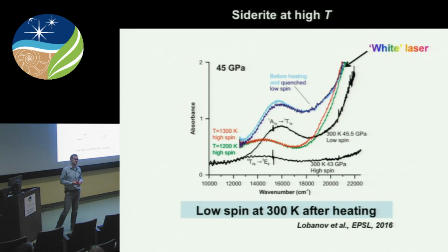Well, we collect thermal background separately, but at this low temperature, at 1200 and 1300 Kelvin, we essentially get zero thermal background because we're using a gated detector. And our white laser is so much brighter than conventional light sources, so we don't have to worry about that. We do have to worry about that at higher temperatures, and this is the reason why this method is difficult to use at temperatures above 3000 Kelvin. But I will talk about that a little later.